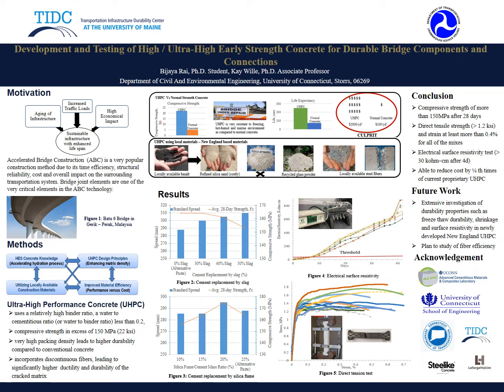Very high packing density of the matrix is the key for strength and durability properties of UHPC. If we compare UHPC with normal strength concrete, the compressive strength is more than 4 times greater. It is very resistant to freeze thaw, hot and humid, and marine environments. It requires less maintenance, and the life of UHPC can be expected to be more than 200 years.